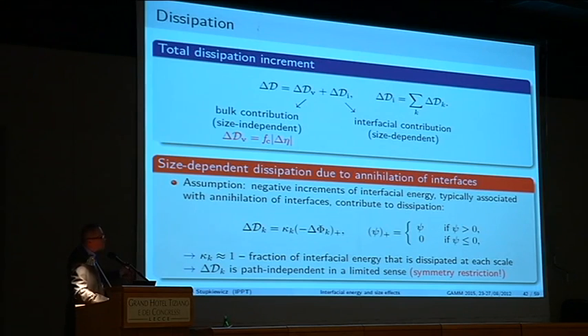And here we adopt an assumption. One can agree, one cannot. This is our assumption, where we assume that the negative increments of interfacial energy contribute to dissipation. So if you think that you deform your material, you induce some new interfaces, which means that you pump energy into the free energy of the system. However, whenever an interface disappears, it is a dynamic event, and this energy cannot be reverted to useful free energy, so it's dissipated. And this is our assumption, and we assume that essentially all of these kappas are close to unity, and whenever the interfacial energy decreases, we assume that this contributes to dissipation. And that way we get a size-dependent contribution to the total dissipation.